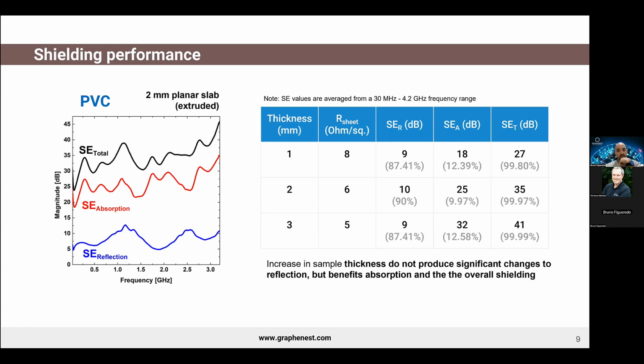On the other hand, increasing the thickness is benefiting the absorption mechanism and the overall shielding. So at 1 millimeter thick, we have 27 decibels of total attenuation, while at 3 millimeter thick, we have 41 decibels of attenuation with this graphene-based PVC. So this is very well aligned with theory because the reflection mechanism of shielding is impacted by the surface conductivity of the sample, while the absorption depends on the thickness of the sample. But we can discuss this theory in a following session after this webinar, if you have some interest.